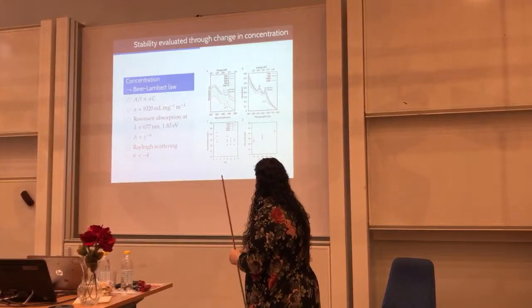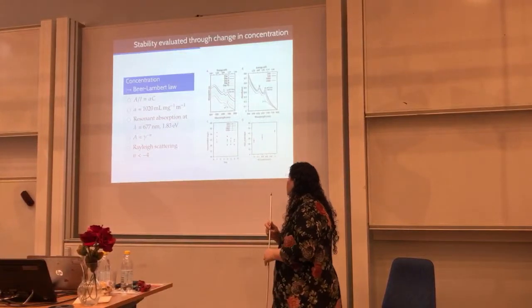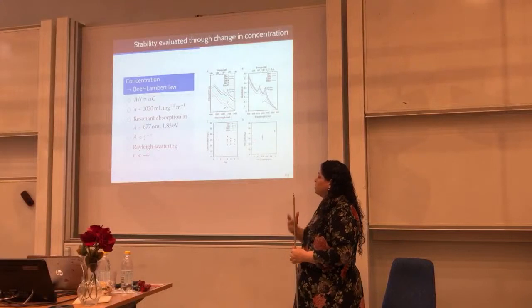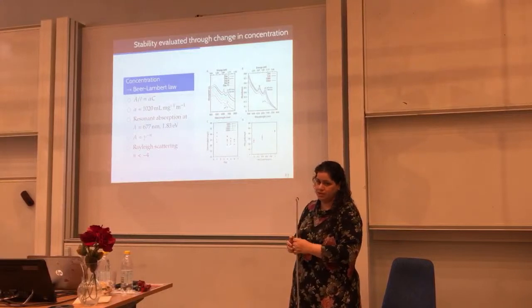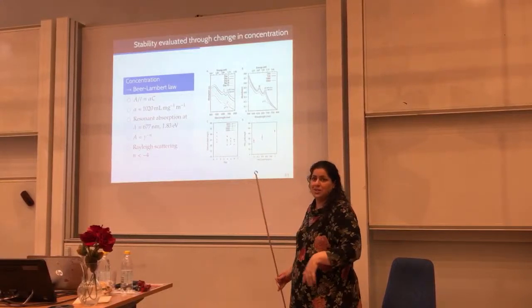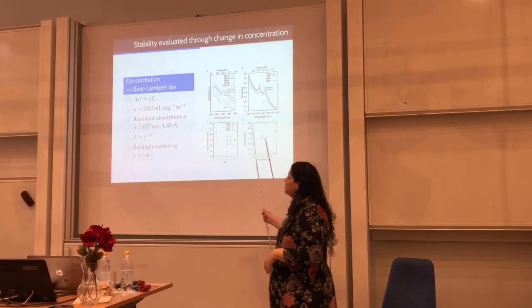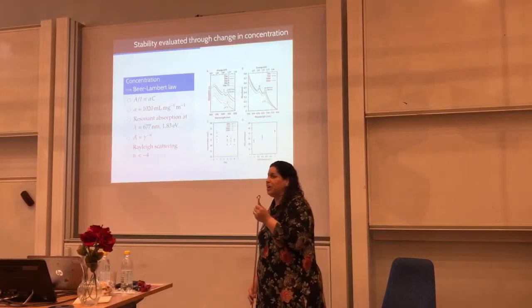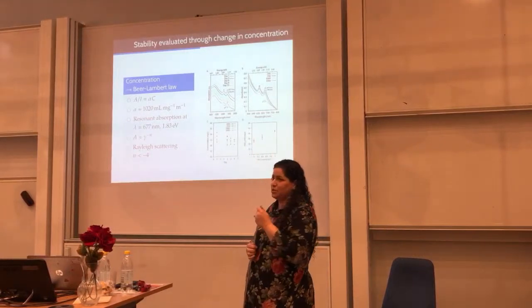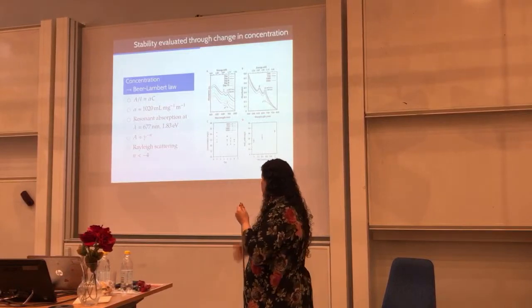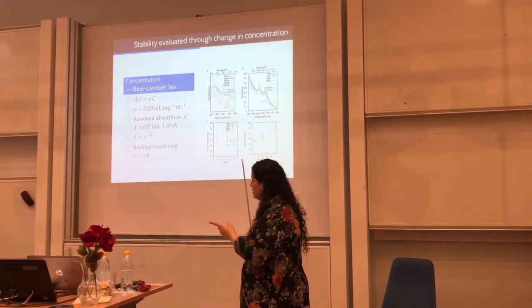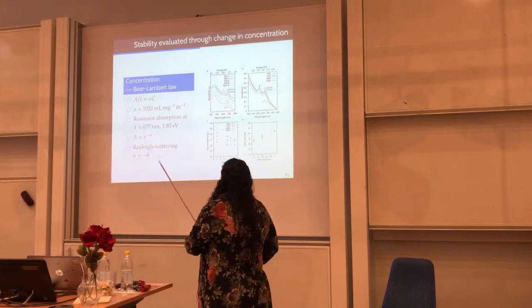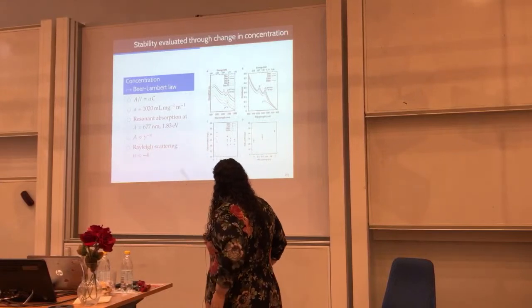Why? Because in the initial papers from Jonathan Coleman that I follow, they always subtract the background to measure the concentration. But it's not necessary to do it anymore, because they found that it doesn't affect the concentration so much. But still, it's not wrong. It's just a different approach. How do we measure the concentration?